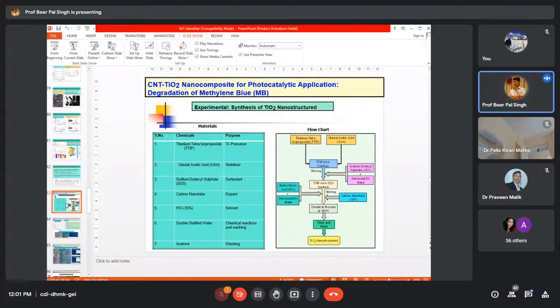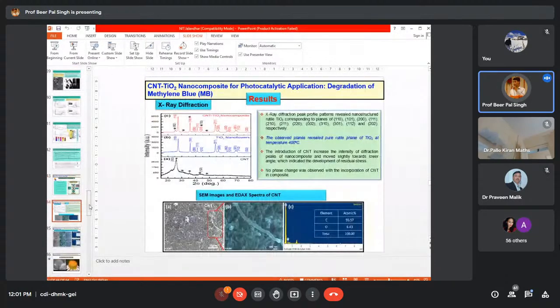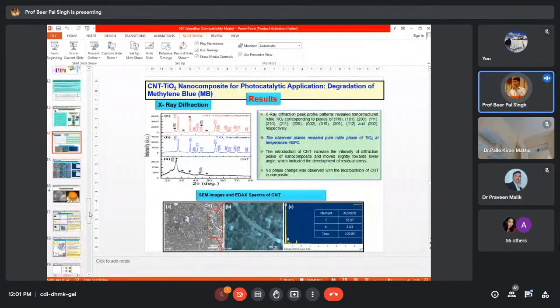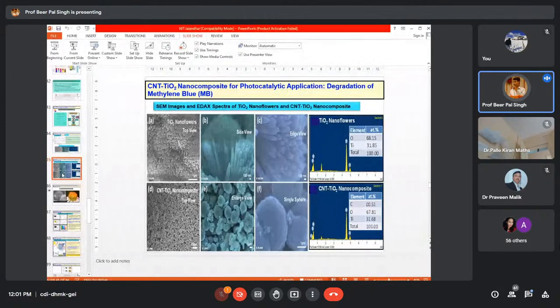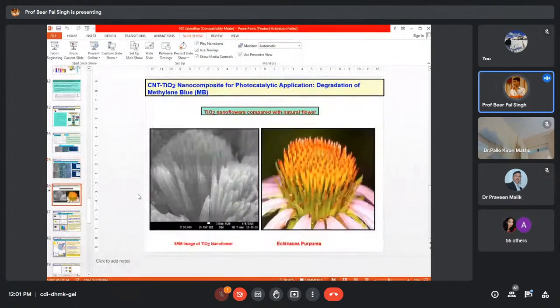of methylene blue. We synthesized it by the hydrothermal method, and ultimately we characterized it by XRD and SEM. In that case, we found a very wonderful structure. We found nanoflower-like structures, and we used that nanoflower structure for photocatalytic degradation of methylene blue. This is the image of the TiO2 nanoflower.